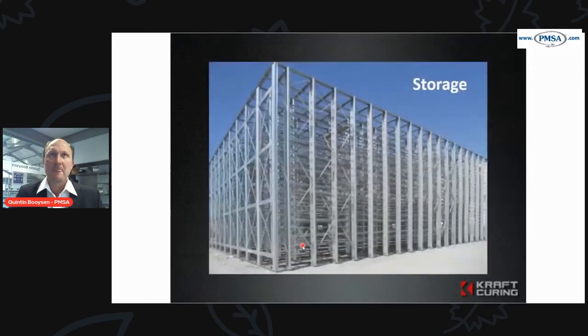Now we're going to go into a few curing systems to give you an idea. This would be the storage facility before it's insulated. In a brick and block plant, there are several layers here. You can see up to 20, we do up to 22 stages of bricks and blocks and paving. We then cover this whole storage area with insulation and sheeting so that we capture all that heat inside, that we don't lose that free heat from the exothermic reaction. We use that heat to help accelerate the hydration process and the hardening of the concrete, especially in those first 24 hours.